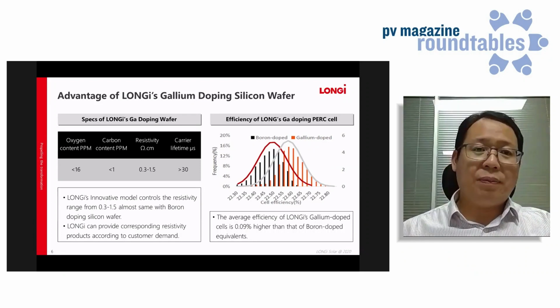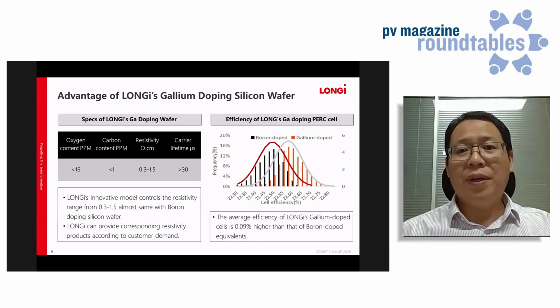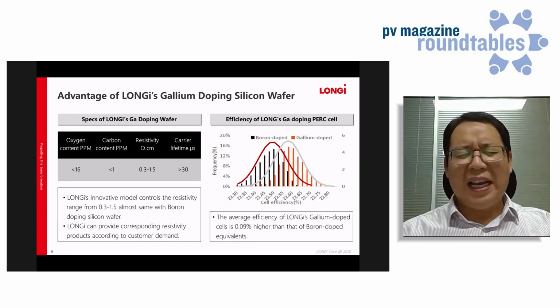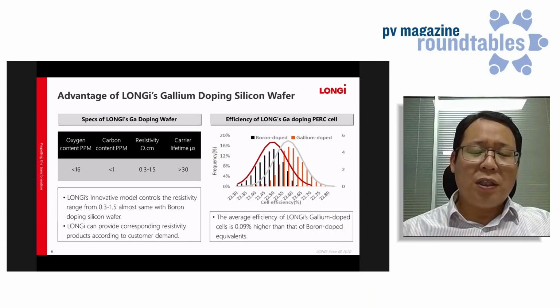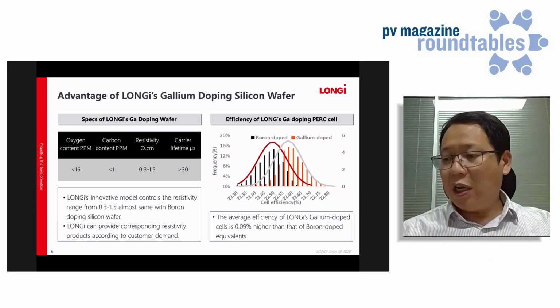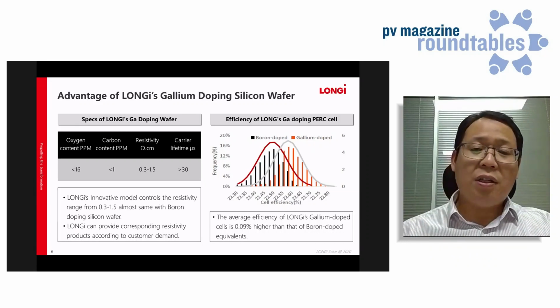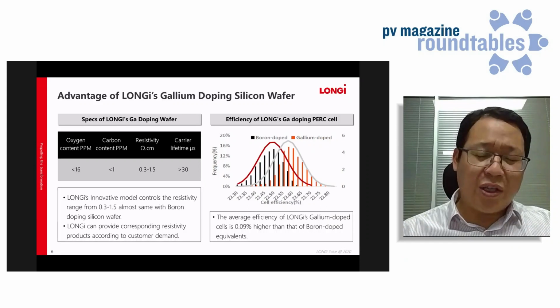This page is about the advantage of the gallium doping silicon wafer of LONGi Solar. Although the gallium doped wafer has a better quality, in the production procedure it's not so easy to control the quality, since for the gallium element, the segregation coefficient is higher than boron, so it's not easy to control the resistivity of the wafer. LONGi Solar worked on it for quite a long time, and till now we have a very good result on it. For LONGi, we control the resistivity of the wafer very well.